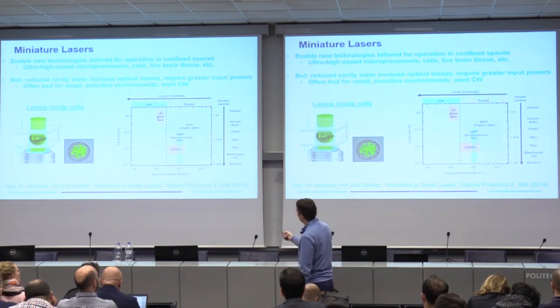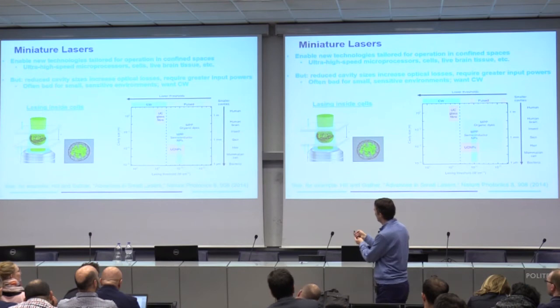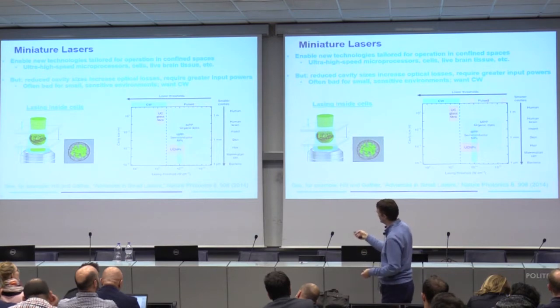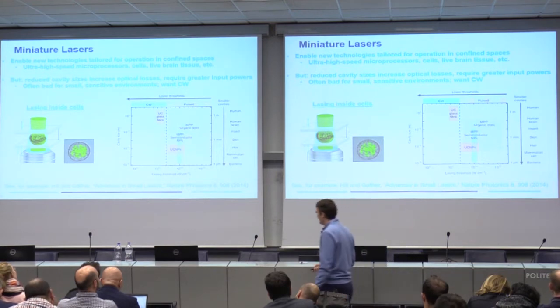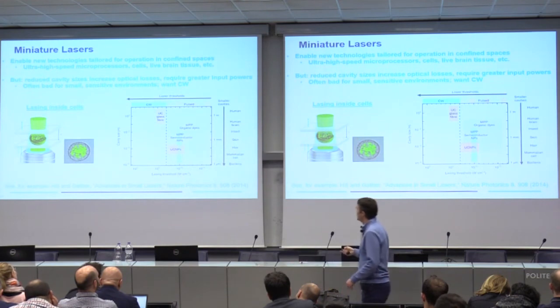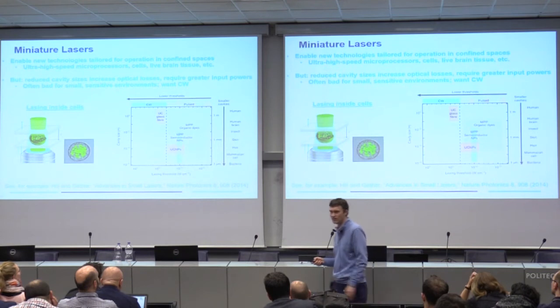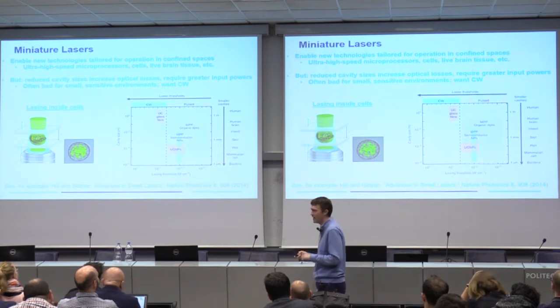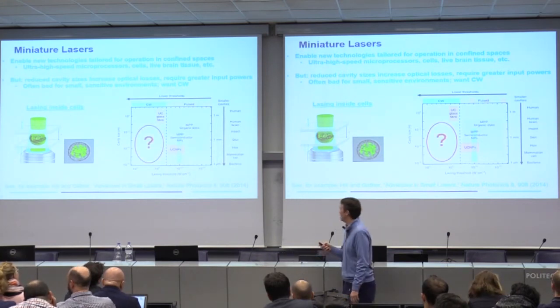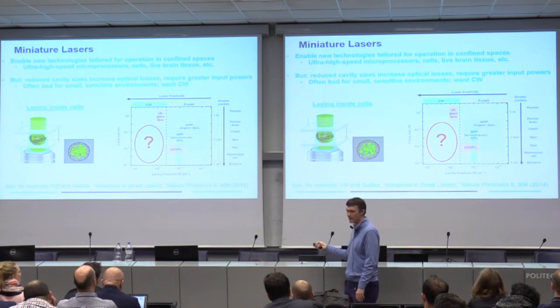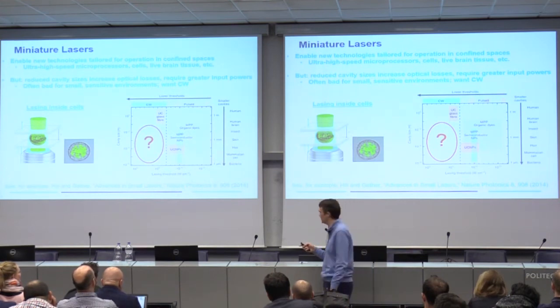And so what I'm showing here is a plot comparing smaller cavities, sort of on biological scales, on the right axis, and laser thresholds on the x-axis. You can see that most small lasers, especially nonlinear lasers, all have to use pulsed operation to get pumped because they need these high instantaneous intensities to work. And only for very large lasers can they make CW lasers. All right, so there's this big empty spot down here. Can you make them small and have low threshold? That's what we're trying to fill.